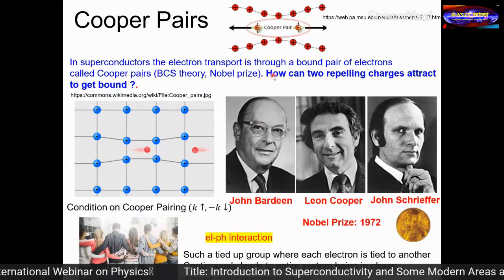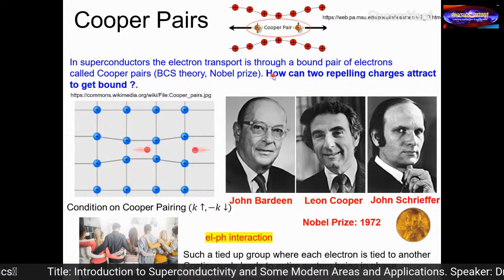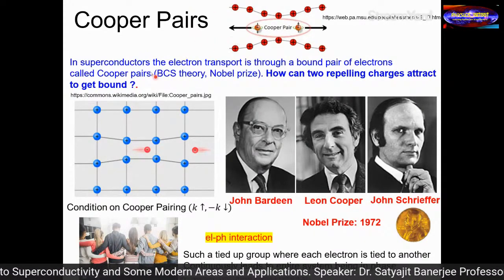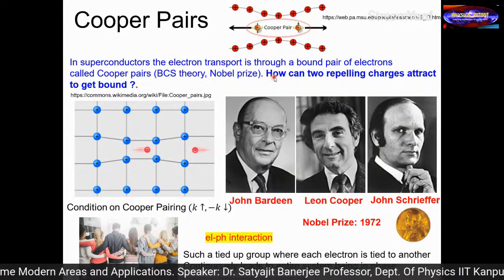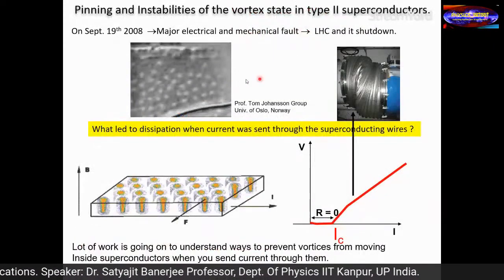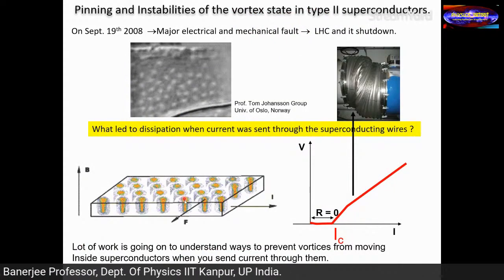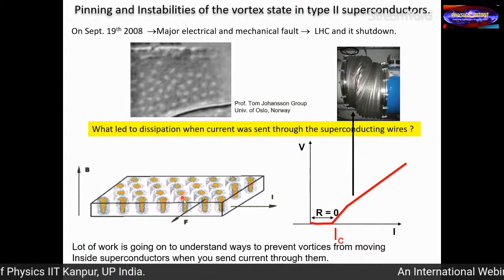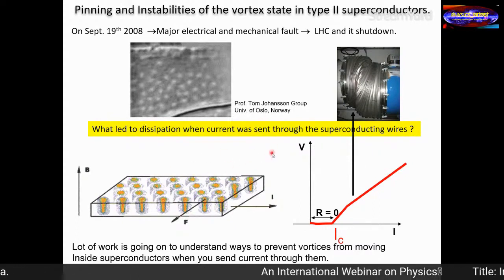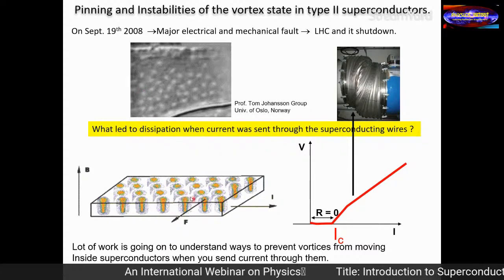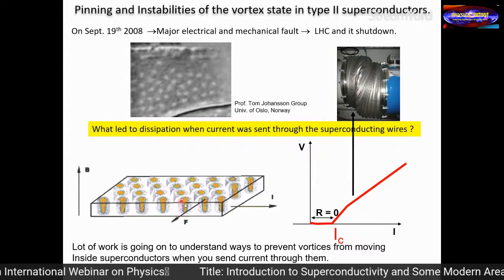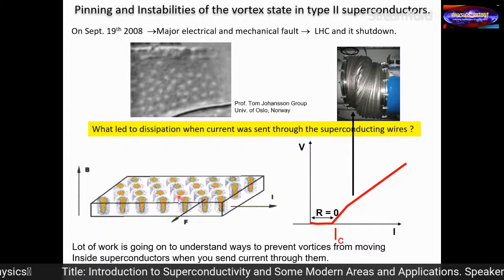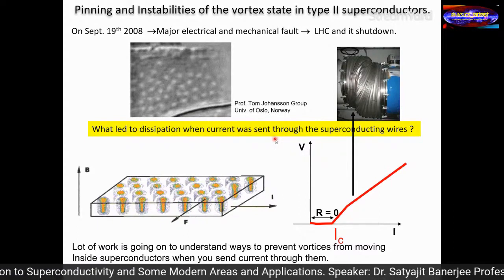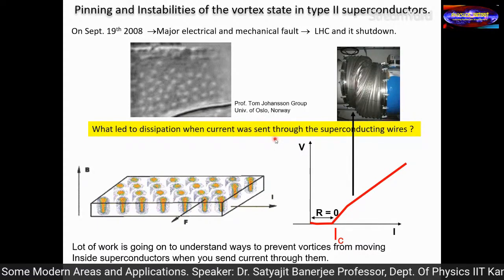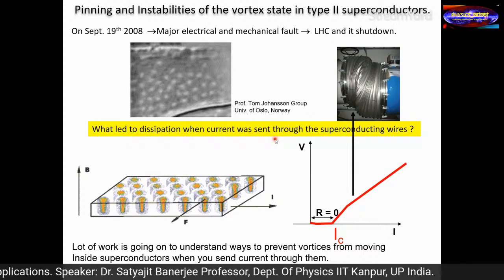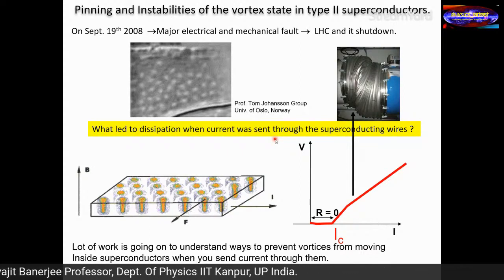Now, two more points, which is Cooper pairing. Very briefly, the idea of how the superconducting state emerges. When people measured the magnetic flux inside the vortex, they found that this flux is related to the charge carriers in the superconductor. The amount of magnetic flux is related to the charges circulating around the superconductor. And when they measured the amount of charge circulating in the superconducting state, they found it was not e, the electronic charge, but twice the electronic charge. Namely, the charge carriers inside the superconducting state are not e, but 2e.